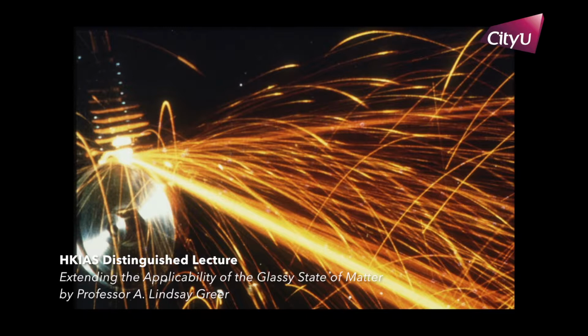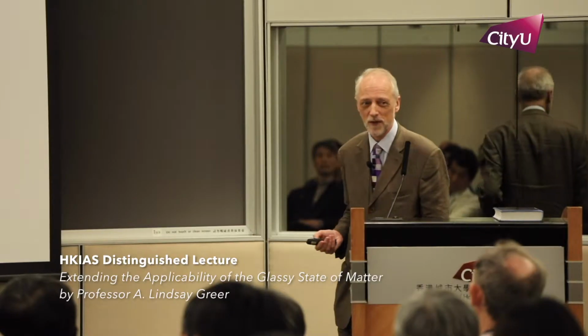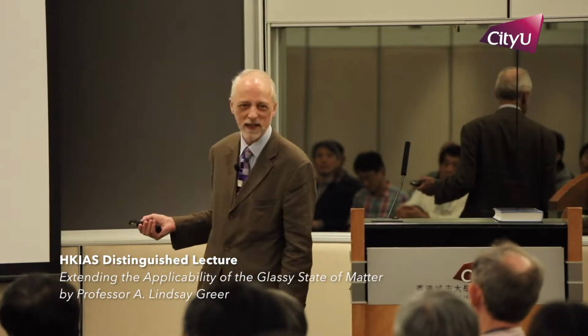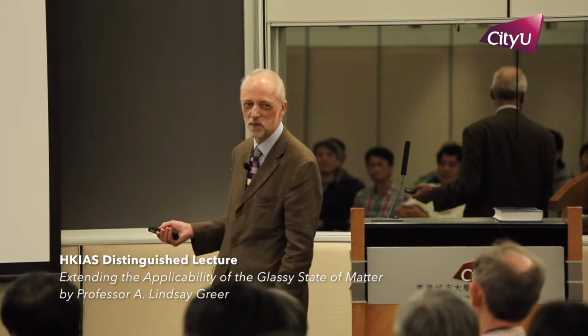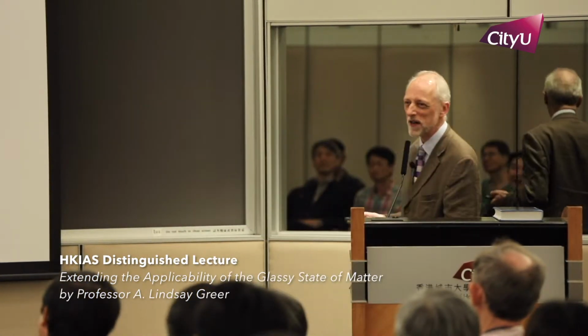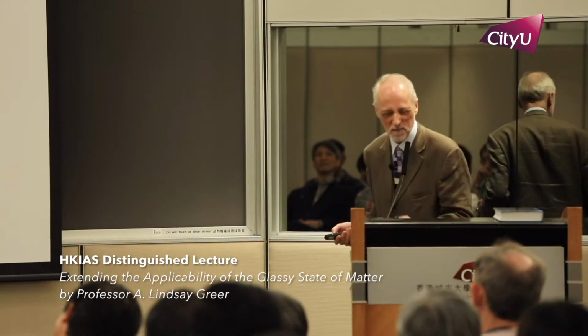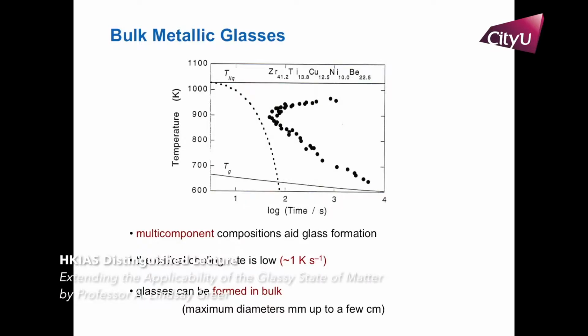And classically, that was obtained by squirting hot liquid metal onto the rim of a rapidly rotating wheel, and you get a ribbon coming off. I have to apologize to the experts in the audience. They will immediately know that this is an example of a production run going dramatically wrong, because you shouldn't have all these sparks flying in every direction. But this is just a more pretty picture. But it gives you an idea that things are going pretty fast here, and the ribbon is some tens of micrometers thick only.